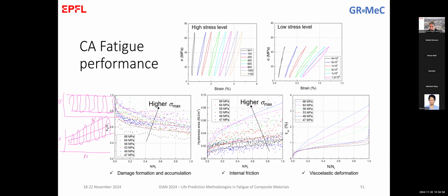So the average strain of this cycle is here, of that cycle is there, of that cycle is there. You will see this also as drifting of the fatigue cycles, of the high hysteresis loop cycles. There are materials that are not viscoelastic, and so cycles that are all around the same value: the cycle for the next, and the cycle for the next. Sorry, they should go up to the same stress, but they look like that. What I show here is a drop of the stiffness because of damage, but there is no viscoelastic effect. There is no drift, so all the cycles are around the same average value.